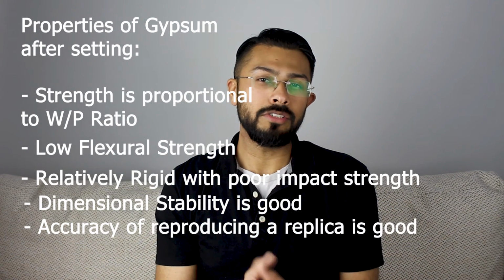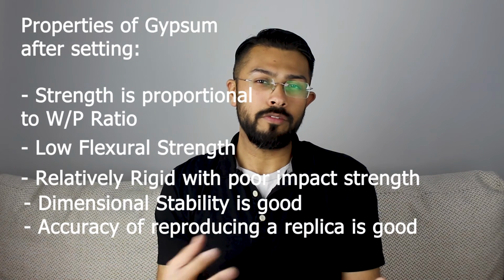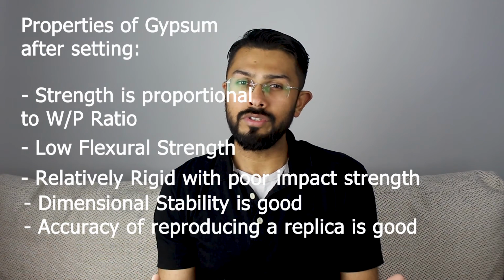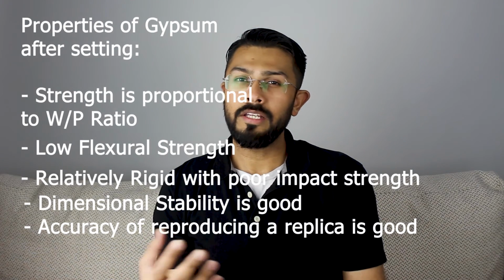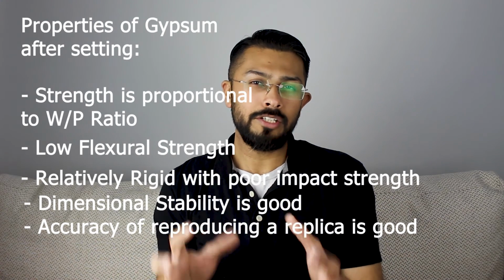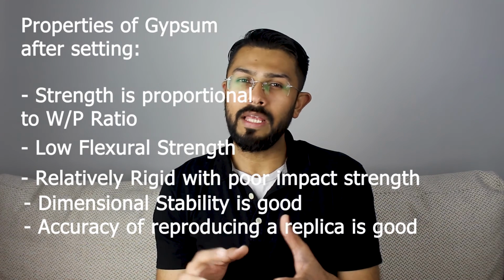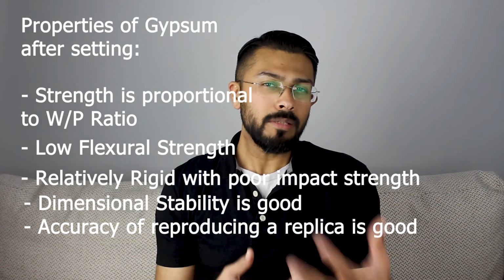The ability of dental gypsum products to reproduce surface details of hard or soft tissues, either directly or from impressions, is central to their suitability as model and die materials. This ability is judged by measuring the extent to which accurately machined lines in a block of stainless steel can be reproduced in a sample of the material, as in the gypsum material is poured over a block of stainless steel that has fine grooves or lines engraved on it.